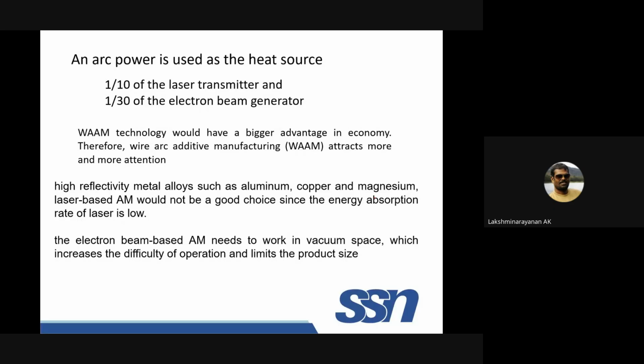Why do we want to go for wire arc when you have laser and electron beam? Yes, the arc power is used to deposit. With respect to the deposition rate, it is 10 times that of the laser and 30 times that of the electron beam. That makes it highly economical with respect to the deposition rate. Deposition rates in laser or electron beam are very, very low. Whereas if you go for wire arc additive manufacturing, for example, if you use the GTAW process, gas tungsten arc welding process,